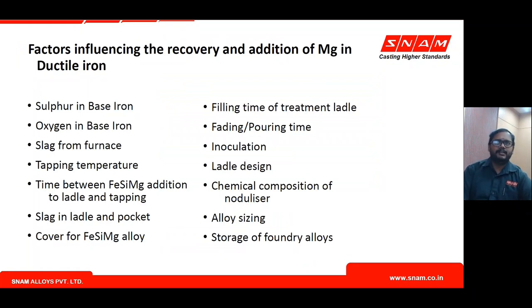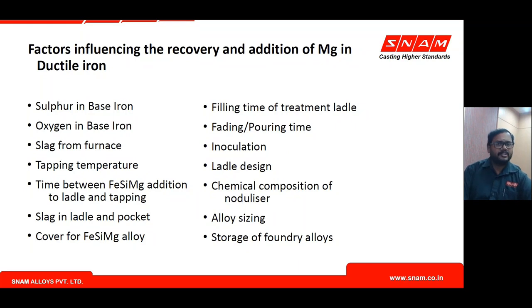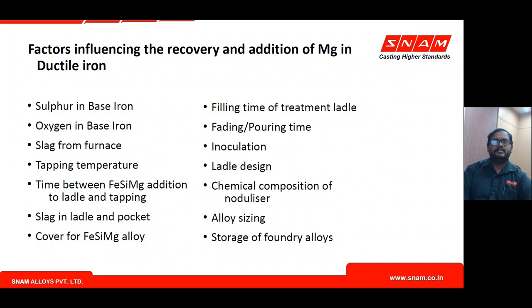Other parameters influencing magnesium recovery include sulfur content in the base metal, oxygen content in the base metal — which is difficult to measure directly, but indirect indicators include thermal analysis and furnace slag, since oxidized slags entering the treatment ladle cause magnesium to form magnesium oxides, thus losing magnesium. Tapping temperature has a direct influence on magnesium recovery.